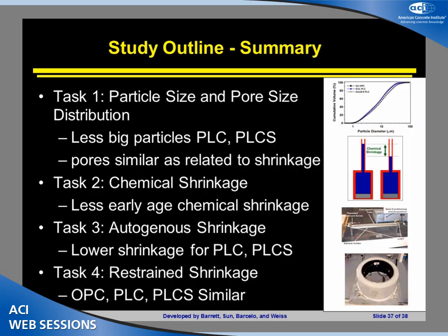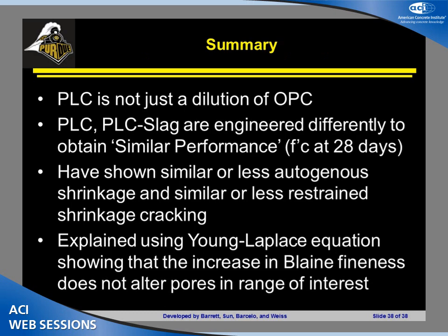So if we want to get into some of the main conclusions of the last part of this, particle size and particle size distribution, the big thing we see in the PLC and the PLC slag systems as compared to the OPC system is really less big particles and more of the small particles being the ground limestone. It's really the ground limestone that's the fine particles. The pore size, though, as it relates to shrinkage is very, very similar in these mixtures, which means that we're going to have similar shrinkage, and I think we've shown that. We see slightly less early age chemical shrinkage in the slag system, but the other systems we see being very similar, mainly due to the finer grind. We see slightly lower shrinkage for the PLC slag system, very similar for the PLC and OPC, and again for the OPC, PLC, and PLCS, very similar restrained shrinkage in the overall takeaway.